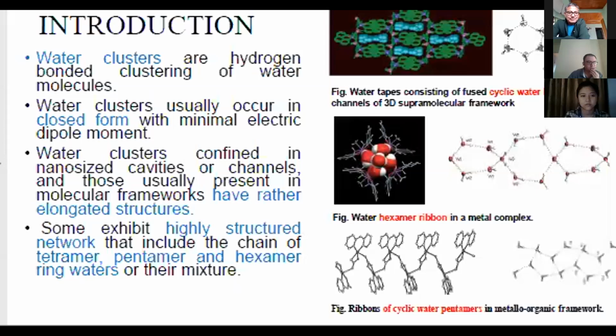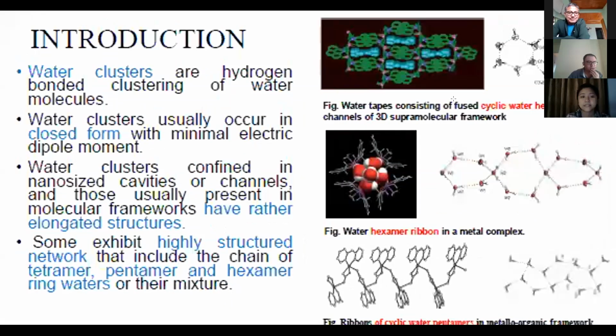For example, in one of the studies, they have found that fused cyclic water hexamers are found in the channels of a 3D supramolecular framework. Also, water hexamer ribbons are found in metal complexes, and ribbons of cyclic water pentamer are found in a metallo-organic framework. These elongated structures have a specific geometric pattern, and they are not stable in isolation. However, when confined in nanocavities, these structures exist. And when this confining framework is removed, the system collapses and gets back to its closed form.